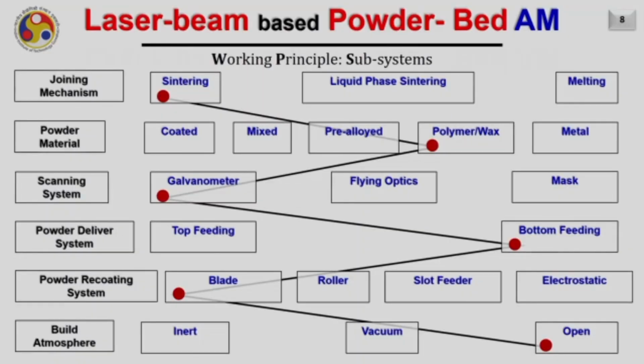Another slight modification in the system could be, as the joining is by the sintering mechanism, the powder material will be polymer, a galvanometer will be used for scanning the powder bed, with bottom feeding of the powder, and a blade will be used to spread the layer onto the powder bed, and then an open environment will be used instead of any inert or vacuum environment. So, this is typically the latest system of laser beam based polymer powder bed additive manufacturing.